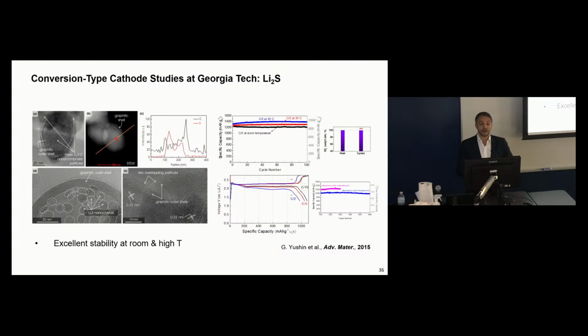And so typically when you charge-discharge batteries at high temperatures, they tend to degrade faster. But here we demonstrated, again, you can retain very high stability, very high capacity too, at elevated temperatures, 35, 45 C. And the difference between charge and discharge, called hysteresis, is very small. It means that the energy losses are small even though you use a conversion process. Sometimes people believe that if you have a conversion process, if you have to break and restore chemical bonds, you will lose a lot of energy. You do lose more energy, but it is still very small compared to everything else. So you can have a small hysteresis, you can have good energy efficiency in this process.